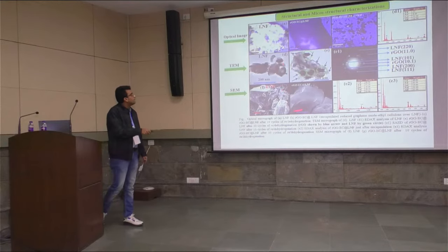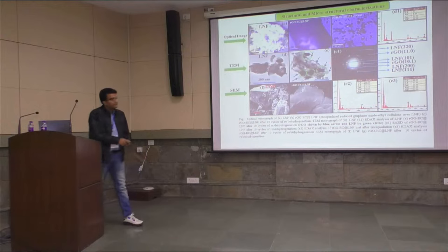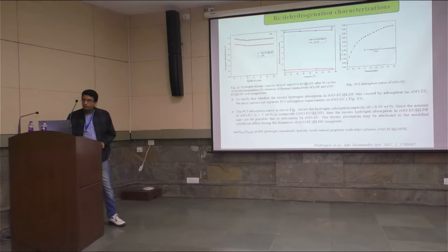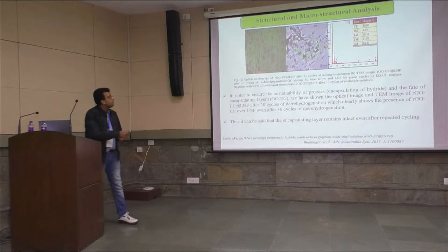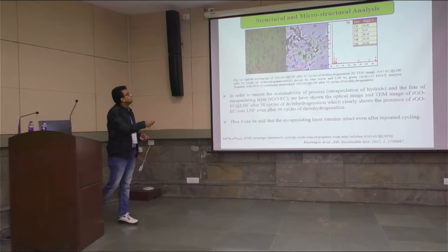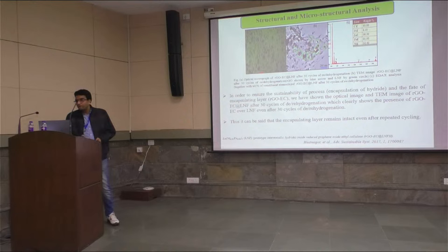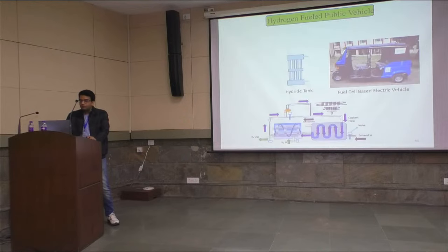So these are the TEM images which show that the hydride are engulfed inside the graphene, with the selected area diffraction pattern. We have shown that the graphene does not affect the hydrogen storage capacity of the material, and it even remained intact after 30 or even 30 cycles. We have done up to 30 cycles, the hydride material remains as it is, graphene remains as it is.